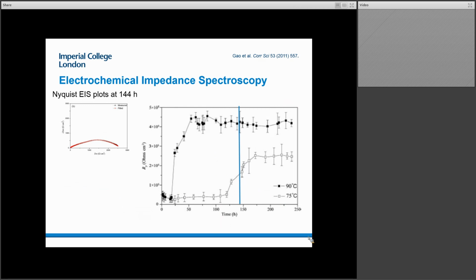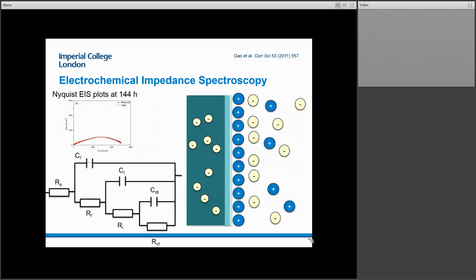So if we go from there and we think about, well, what was happening in that intermediate step? Because we could hypothesize there were all sorts of interesting things happening. And the reality at that point is you might have to draw several circuit models and test them all out. So I'm going to jump ahead in this particular case, and I'm going to guess that perhaps we have a two-layer structure. And so I've illustrated that on the right, sort of that idea that we had some sort of layer, and perhaps the layers changed in thickness, I don't know, but another layer is certainly found on top of it.